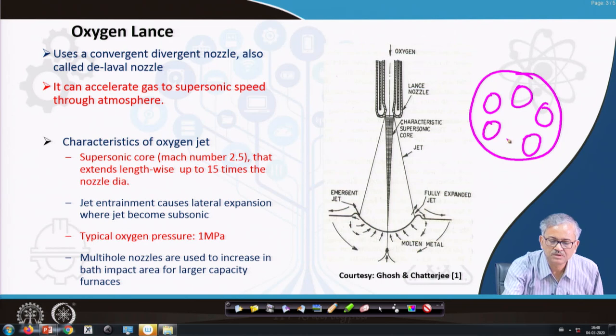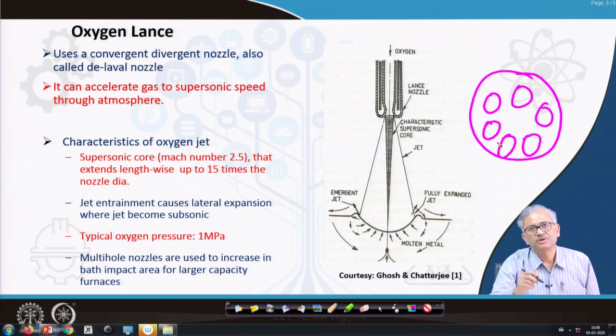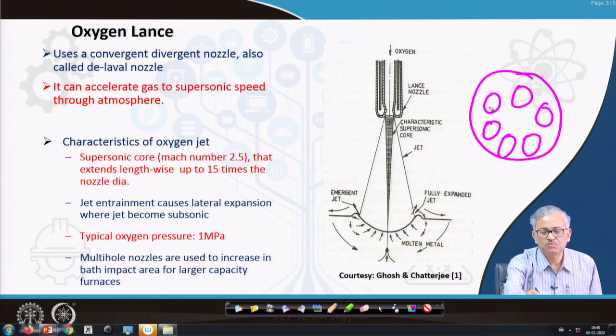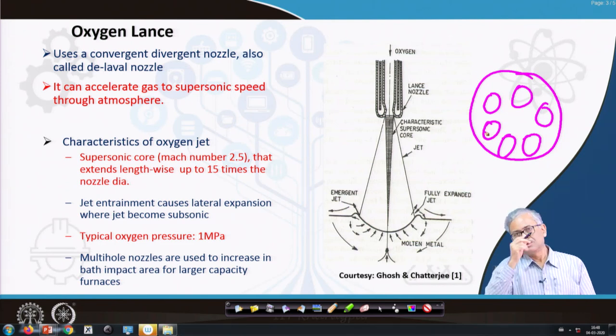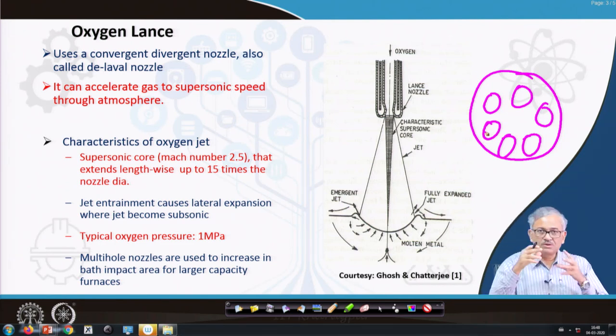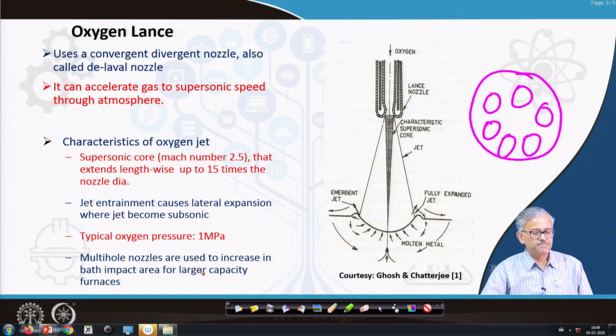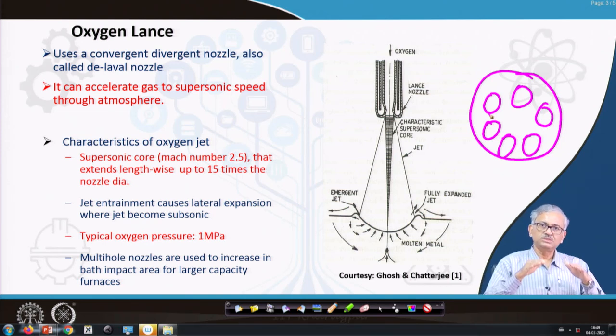So, the number of holes, these are all convergent-divergent nozzles, 1, 2, 3, 4, 5, 6, suppose 6 convergent-divergent nozzles are there. And the nozzles are configured in such a way that they do not overlap with each other, because they will be independent. And then it basically increases the total impact area of the bath. A single nozzle has this much impact area. If you have 6 nozzles, then it will have more impact area of the bath, and that is required for a big capacity furnace. So there, multi nozzles are used. In the lance you have a single lance, but you do not use one nozzle, you have a multi-nozzle system, such that the impact of the oxygen jet with the